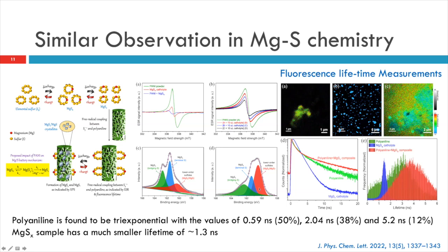What we have seen here is that polyaniline, when you measure only polyaniline, shows three types of lifetimes: about 50% shows 0.59 nanosecond, around 40% shows 2 nanoseconds, and a very small amount shows 5.2 nanoseconds. When we do the same lifetime experiment for photoluminescence, we see that magnesium sulfide, the catholyte, actually shows a smaller time scale, like 1.3. That shows there is a possibility that polyaniline free radicals can combine with the polysulfide from the magnesium sulfur. So similar explanations to what we observed are given.